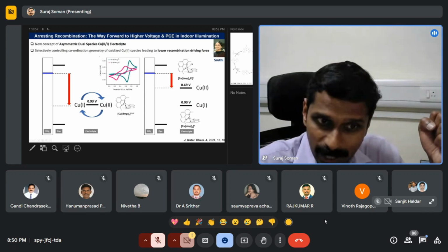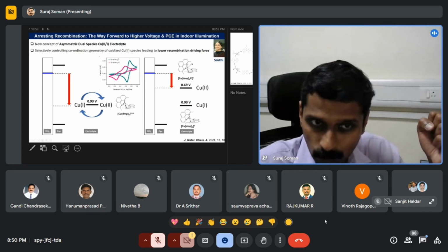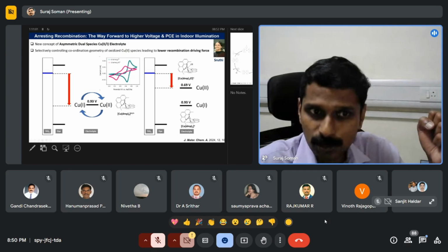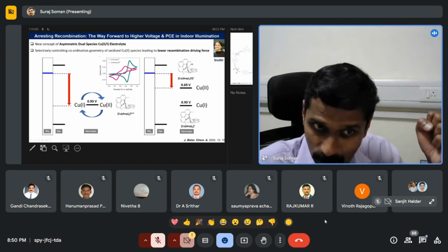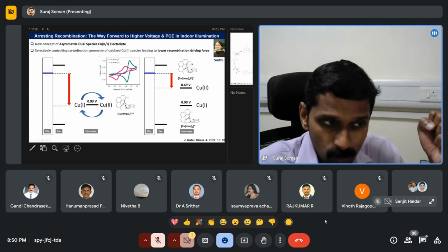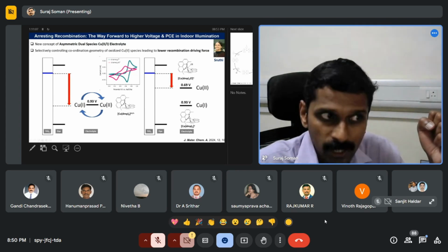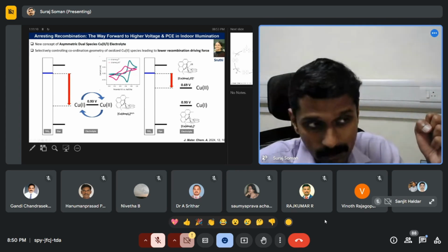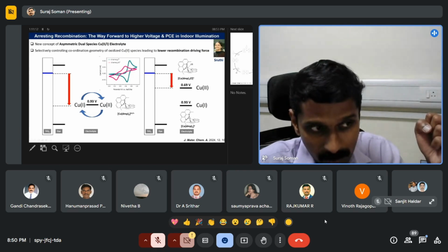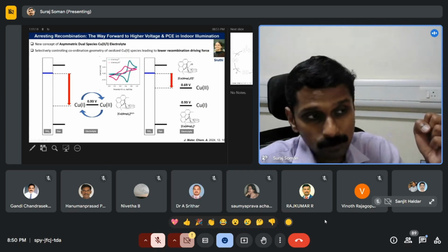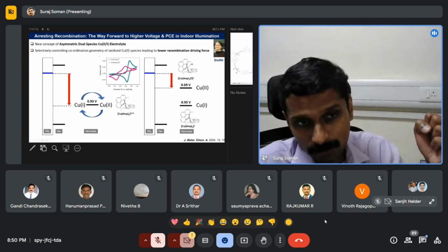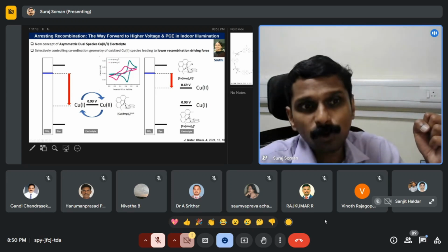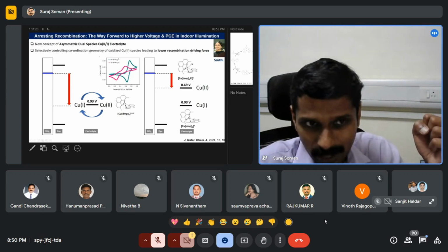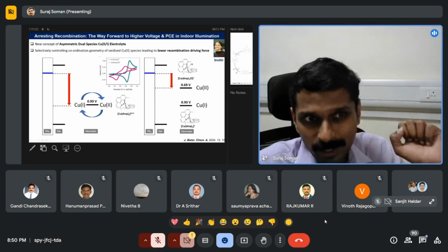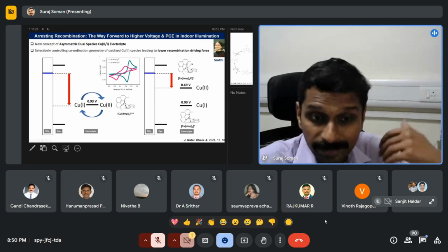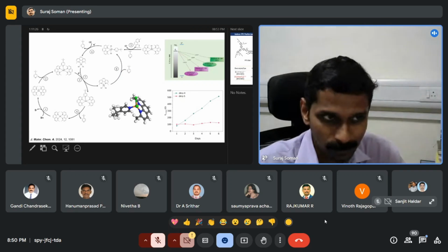So conventionally, you are having 0.93 volt, but for the oxidized species, it is 0.69 volt. So what you see here in the red arrow is the recombination driving force. In the conventional system, you are having this much recombination driving force, so the recombination will be very fast. But the moment you go for a smaller one, this one, you are reducing your driving force for recombination. And that reflects in the rest of the parameters.